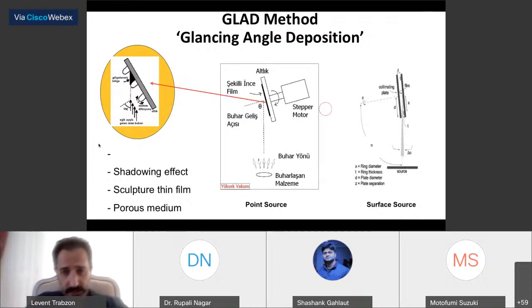We already know that the GLAD method, glancing angle deposition, has been studied widely in the last 3 decades. The basic mechanism behind it is the shadowing effect, and you are able to sculpt the thin film morphology by playing with the deposition parameters. In the end, you obtain a porous medium.